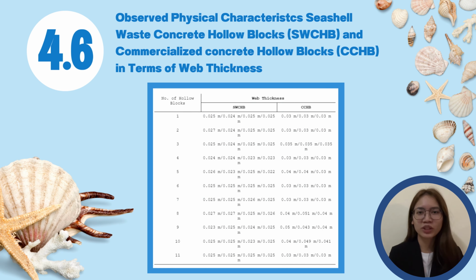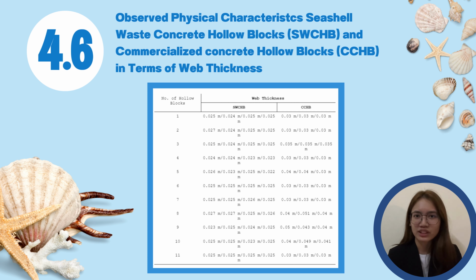This table presents the recorded measurements of the web thickness for two types of blocks, seashell waste concrete hollow blocks and the commercialized concrete hollow blocks. The size of the block's web thickness varies within a range of 0.023 meters to 0.027 meters for SWCHB, while CCHB consistently maintains a web thickness of 0.03 meters across most blocks, although with a few exceptions. Notably, CCHB demonstrates a higher level of uniformity in web thickness measurements compared to SWCHB, where some variations can be observed due to the presence of the three holes or cavities.